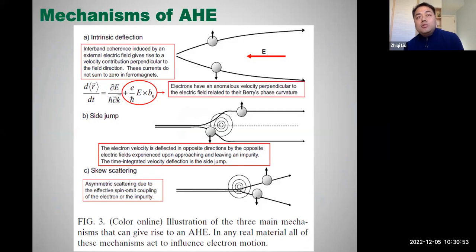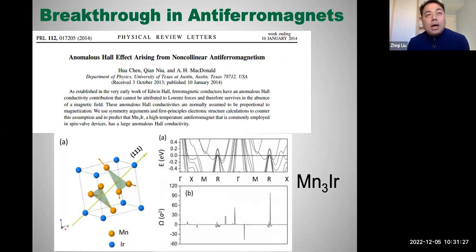The mechanism of the anomalous Hall effect was really controversial since its discovery in 1881, but now people finally have some consensus that most of the contribution comes from the intrinsic deflection, the so-called Berry curvature, and the other contributions are quite minor. Following this understanding, Prof. MacDonald's group, again, predicted there's a large Berry curvature for non-collinear antiferromagnets, for example, manganese-3 iridium and manganese-3 platinum.